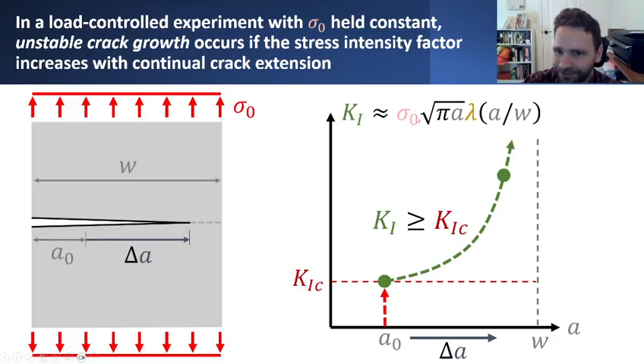So clearly, even if we're holding this far-field value of stress fixed, increasing the crack size due to crack extension will lead to an increasing value of K1. So if the crack extends just a little bit, holding the stress fixed, it means that K1, the stress intensity factor, is going to increase. And at this new point, after the crack has extended a little bit, with the same value of far-field stress, we notice that we're still violating this constraint, that we're still in this scenario where K1 is in excess of the fracture toughness, which means that the crack is going to continue to extend.